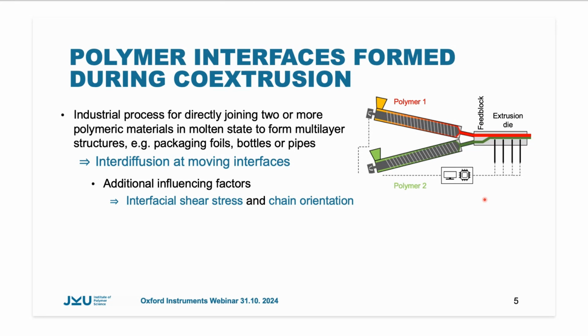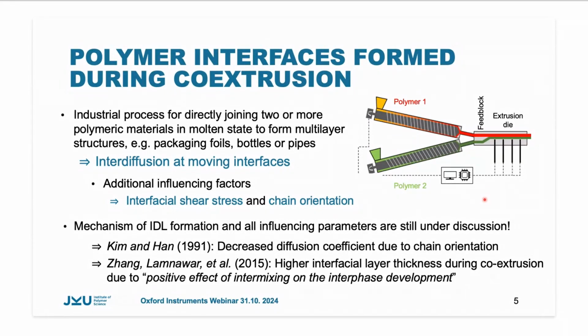Although the technique of co-extrusion has been used for 50 years, the mechanism of interlayer formation and all influencing parameters are still under discussion. There are two different models proposed, one in the beginning of the 90s by Kim and Han, based on theoretical consideration. They suggested a decreased diffusion coefficient due to the chain orientation under shear. In contrast to this, in 2015, the group of Zhang and Lamnawar showed in experimental research that higher interfacial layer thickness occurs during co-extrusion, and they thought that it is due to a positive effect of the intermixing at the interface. Nevertheless, it's not clear what is really going on for the interface formation under shear condition.